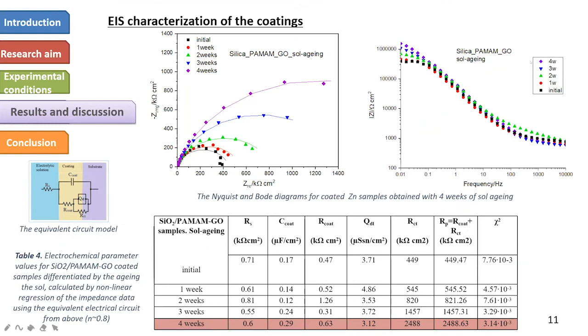And on this slide, we can see the detailed soil aging effect in case of the silica PAMAM-GO samples. On the second week, the coating's Rp value almost doubled compared to the sample coated from the initial precursor sol. After 4 weeks, the polarization resistance reaches 2,488 kiloohms from the 449 kiloohm start value. In the Bode diagram, we can observe that with soil aging, the silica containing PAMAM-GO coating becomes capacitive, which we know from the fact that this part almost becomes a straight line.